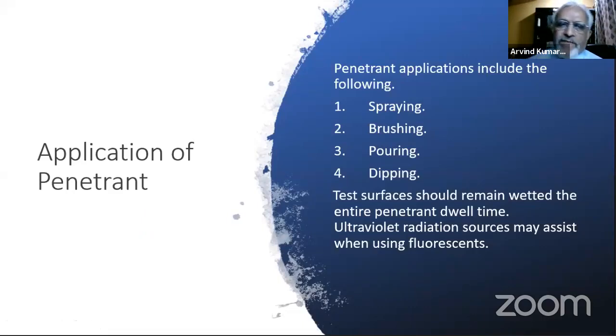Now, as I was saying, you can apply the penetrant in a number of ways. That is by spraying. Spraying is generally what the kit I had shown in the previous slides. We have aerosol cans where you can spray the penetrant. Or it can be also applied by brushing, pouring, or dipping. What we should understand is that whatever method or procedure we have followed as a documented and approved procedure, the same procedure we need to follow in subsequent tests that we do. If I have approved a procedure where the spray is used, then I should follow that only during my penetrant testing. If I change these variables, I have to prove again that what I'm doing is correct and I'm able to detect the defects which I'm supposed to pick up.